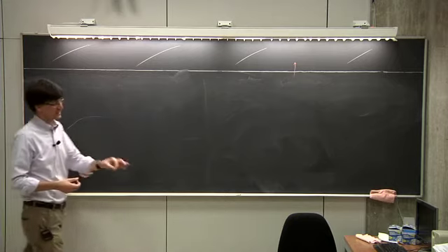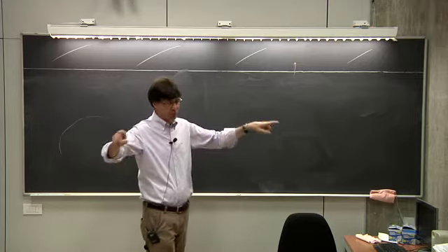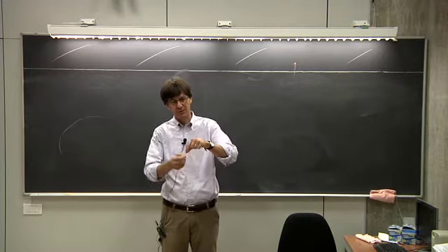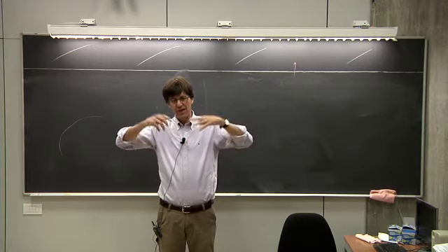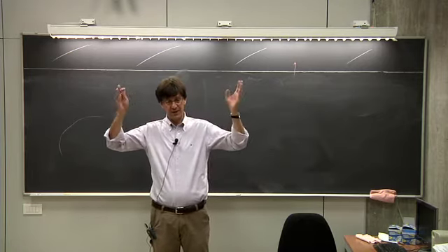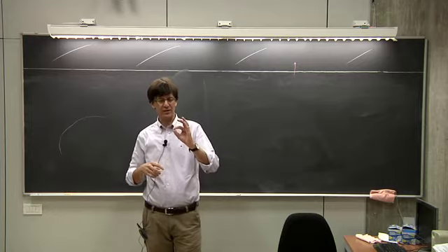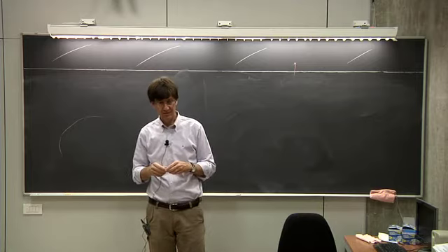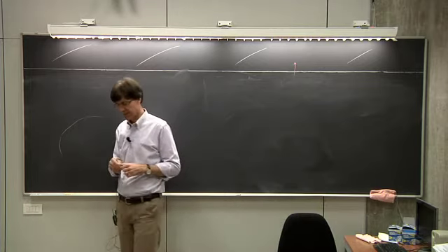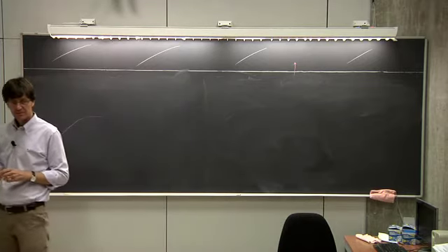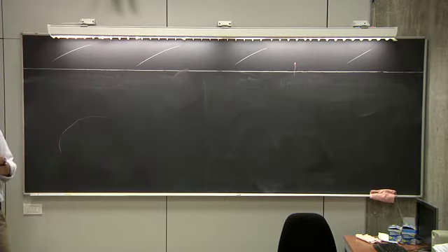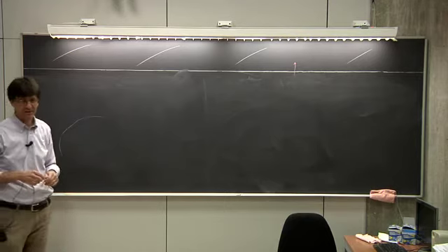Also, you have to think that you are exciting an electron, but this electron has to be able to escape outside the sample. So if you're exciting this electron deep inside the sample, it has to be able to reach the surface and then be emitted. If you're really close to the edge, probably the scattering will prevent the electron from being emitted outside the sample. So you don't want to be really close to the threshold. You want to be much above the threshold in order to measure your kinetic energy properly.